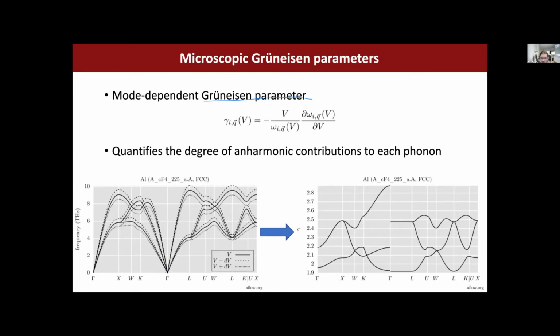Also, the gamma point is a bit special because near the gamma point, you start getting dependency on the direction, and it is illustrated here that you will start getting discontinuities. For example, if you compare the plots on the left and on the right, you see that here you have only 2 branches, and you also have 2 here, but on the right, you have 3 branches. And of course, they also have a different slope. So it's really not possible to connect them in a continuous way at the gamma point, and that's why you start getting these discontinuities.